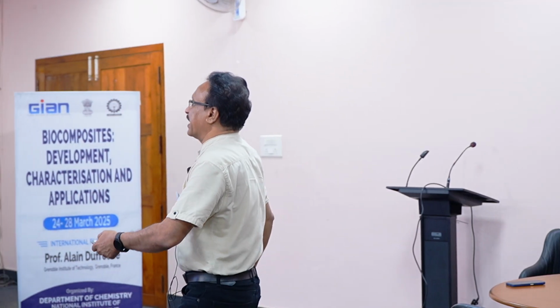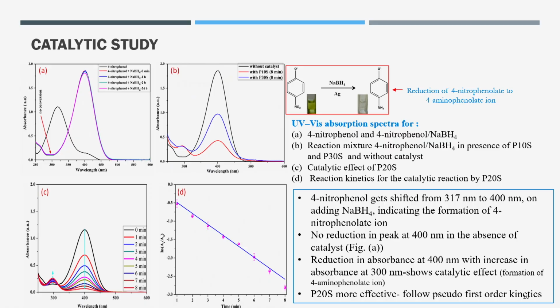It clutches the macromolecular system. So when you try to apply a deformative force, the silver gets reinforced in the system very uniformly, as evidenced by UV. So the system is strengthened, and a very high modulus is derived for the system. So it's another evidence, the sixth evidence for the development of the system. With all that background, we have started using catalytic activity.